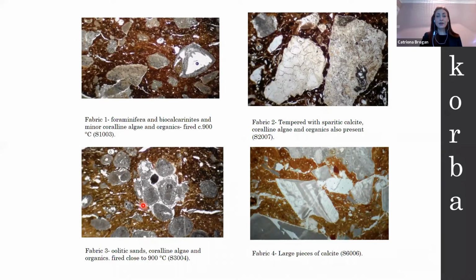Within our sherds, the most common type of fabric was fabric 1, which seems to be full of forams and bioclastic carbonates, and it's also got minor coralline algae and organic material. This can be seen, unfortunately not in this sherd, but if you get black areas, it suggests where an organic has burnt away, and it seems to be quite well fired.